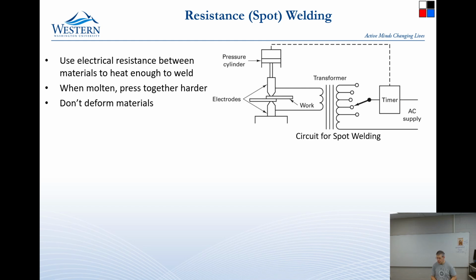The question is why do the two pieces weld together and the electrode doesn't weld to the side? Well, that occasionally happens, but mostly the two pieces weld together. And it's, again, physics being cool, or maybe chemistry, I don't know. At this level, who can tell? Right at the interface is the surface that's oxidized, and that has the highest electrical resistivity. The electrodes are made of copper so they have very low resistivity, and they tend to have a surface that somewhat bites into the oxidized layer on the outside so that it will get good conductivity. When you flow this electricity, especially with a high frequency, the surface at the interface heats up because it has the highest resistivity, and it heats up enough that it will weld those two together.